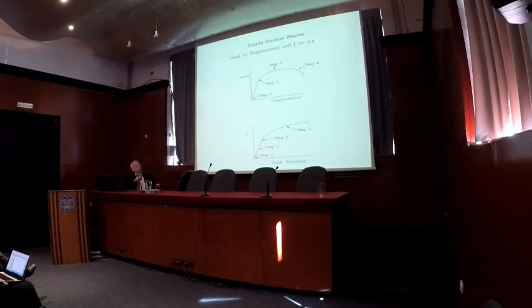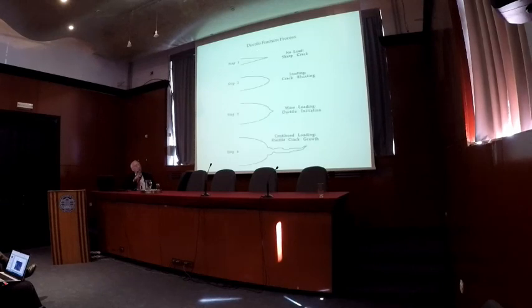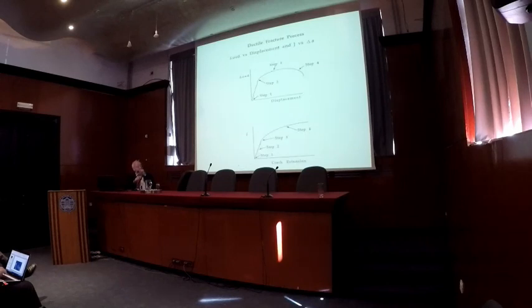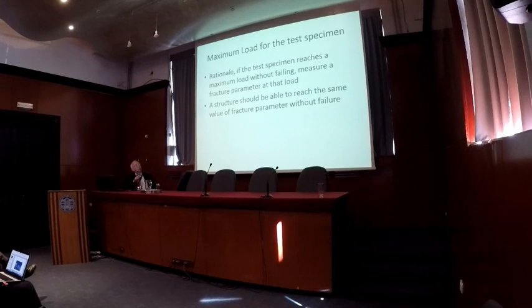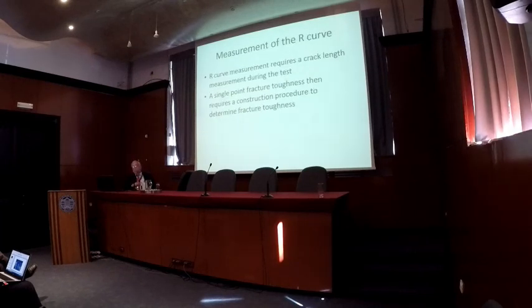So on load and displacement, or on the R curve, here I use J, you can put those four steps. Step one at the beginning, step two when you have geometrical blunting, step three when you get the sharp growth ahead of the blunted crack, which changes the slope significantly, so you get a kind of a bend over there. In the CTOD, they often use maximum load, and they don't use an R curve all the time. They say, if a test specimen reaches maximum load without failing, then the fracture behavior is greater than that. And they assume that the structure should be able to reach the same point without failure. And that's sometimes controversial, that idea.